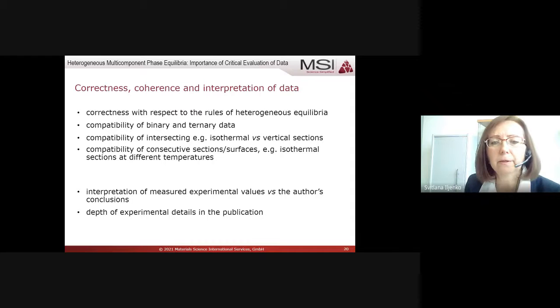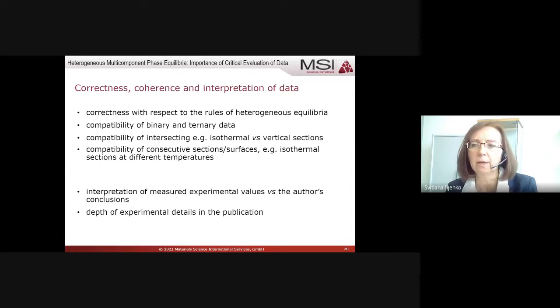So now, what else do we check in the literature when we make critical evaluation? We check the correctness, of course, with respect to the rules of heterogeneous equilibria. Then we check the compatibility between binary and ternary data. And when checking compatibility of binary and ternary data, it is important first to evaluate the data on the binary system and then go back to the ternary. If we find conflicts between binary and ternary systems, then this is indeed a challenging question to decide who is guilty, where is the fault, with the binary or with the ternary data.